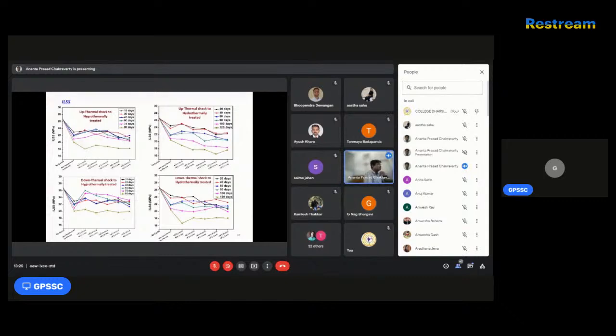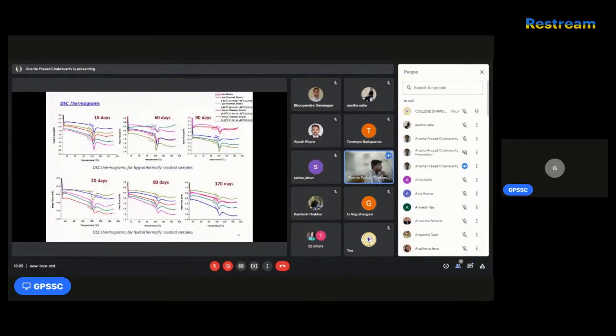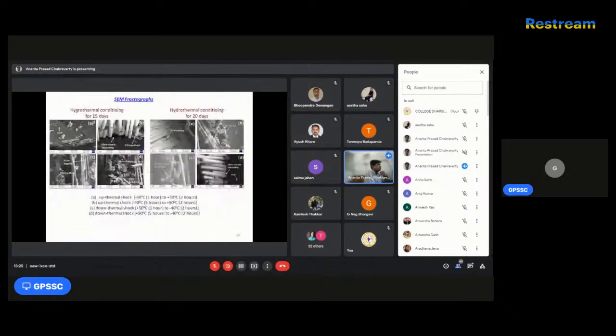With respect to that, the interlaminar shear strength pattern, the zigzag trend, or the extent of damage can be understood with respect to such thermal shocks, and also the glass transition temperature trend can be understood with respect to different extents of thermal shocks, either from higher to lower or lower to higher. And similarly, the scanning electron microscope can give you insight into whether there is any fiber matrix debonding, and if it is debonded, why it is debonded, whether it is due to matrix failure or fiber failure. That can be understood rigorously if you go to at least 500x or 1000x magnification in the scanning electron microscope.